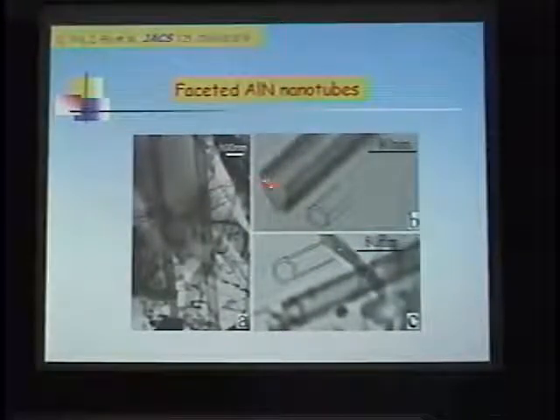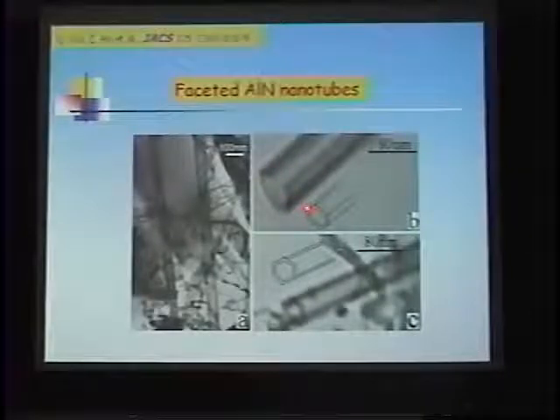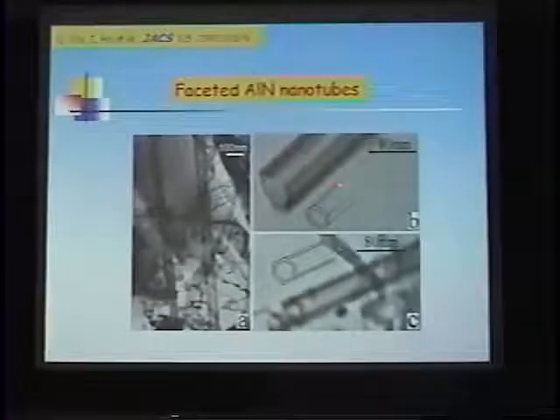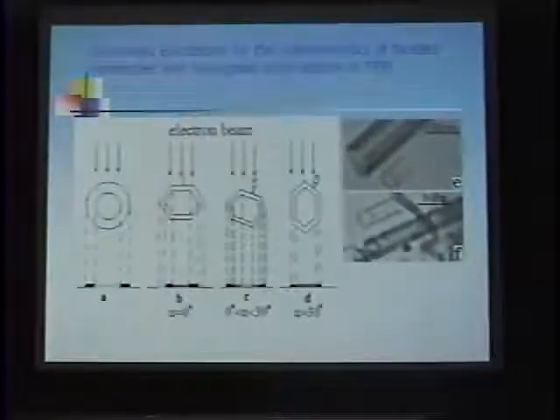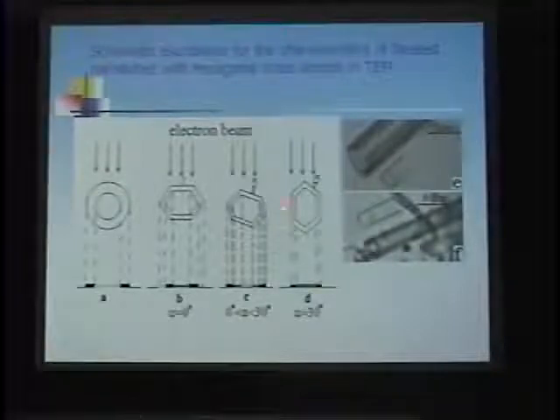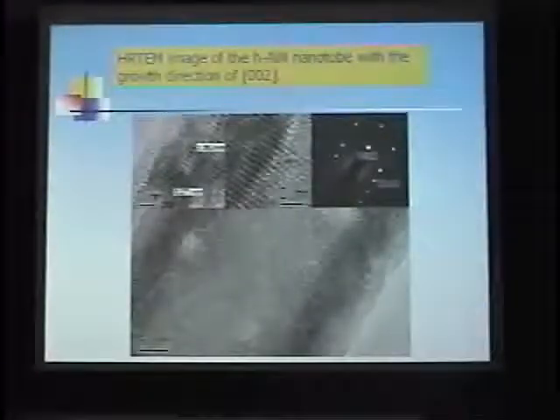You see, the end of this aluminum nitride nanotube lies in such a fashion, and you could see the right hand. And this nanotube is lying in such a fashion. With the hexagonal cross section, the different lying fashions are also reflected in the changing behavior of the contrast along this line. The further characterization I will not explain in detail. This is the explanation of why different lying fashions show different contrast for the nanotubes. And here is a high resolution transmission electron microscope image.